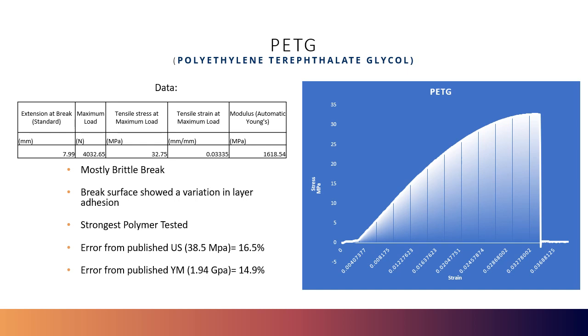First material I tested was PETG. It turned out to be the strongest material overall, and also one of the stiffest. It had a fairly small variation, for my testing samples, to the published material that you can see at the bottom, which I was able to find from the MatterHackers website for the specific printer filament. It broke brittlely, and the